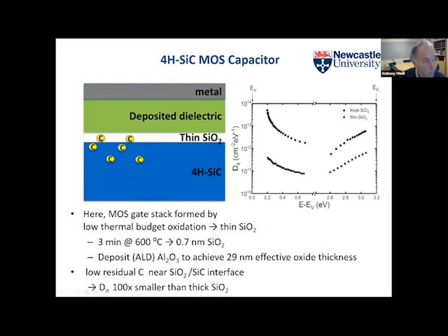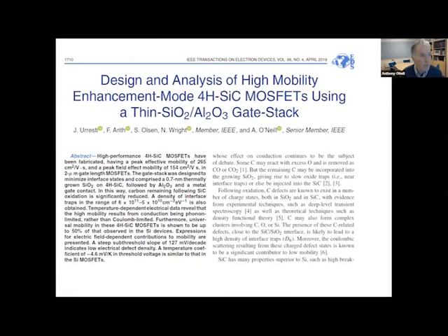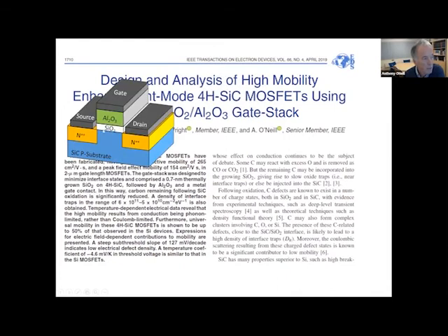So what we chose to do instead was to go to a very thin oxide, create fewer defects. It allowed us to use a deposited dielectric in order to get the appropriate effective oxide thickness. And lo and behold, when we look at the density of interface traps, that came down by about 2 orders of magnitude. So that puts us in a position where we expect, therefore, the MOSFETs to be a lot better. This is just looking at a capacitor structure. So this is some of the work that we published a couple of years ago, looking at the high mobility enhancement mode MOSFETs using this thin silicon dioxide. So this is the idea. So you grow a very thin oxide just here and then deposit the dielectric on top.